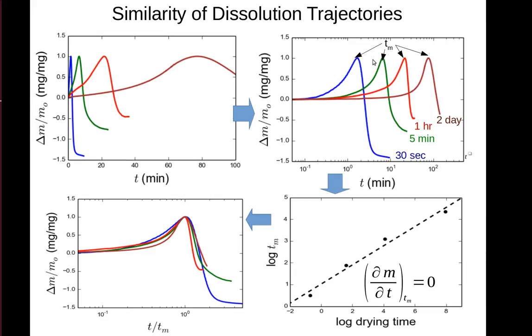If we pick a point on each one of the curves, say the maximum, and plot that maximum versus the drying time, we can fit a curve through that, in this case a line. This relates the drying time to how much they are offset from each other, or a scaling factor. We can then use that scaling factor to scale our curves, and they collapse nicely almost onto a master curve. This conveniently allows us to predict the dissolution rate for other drying times.